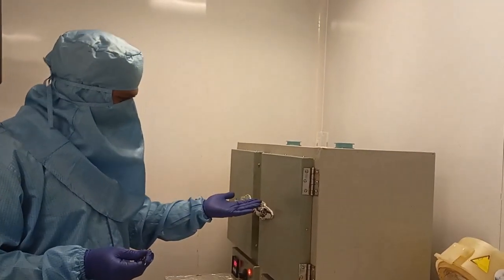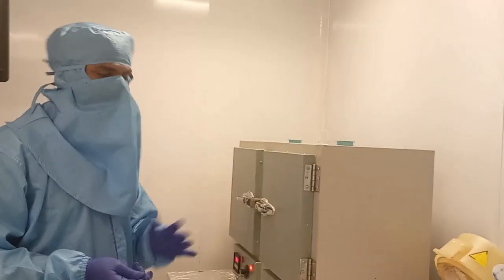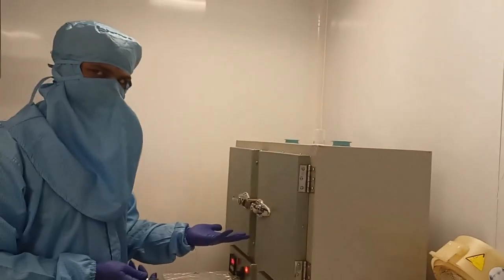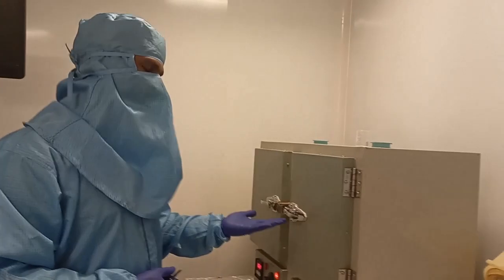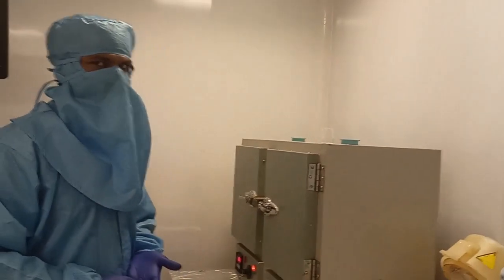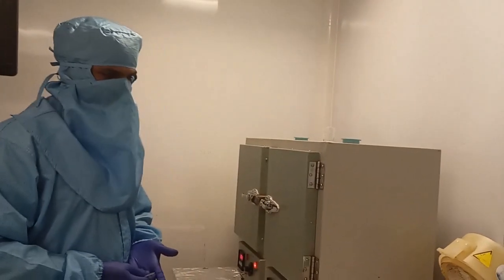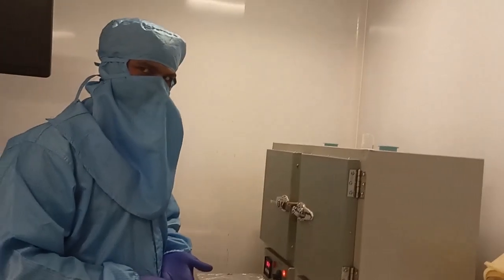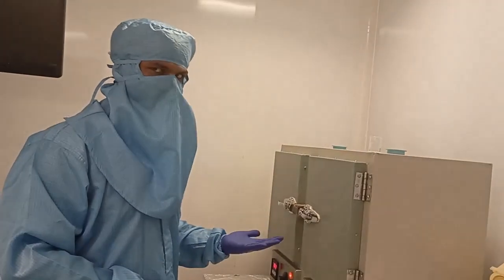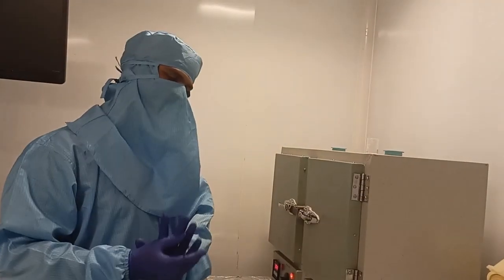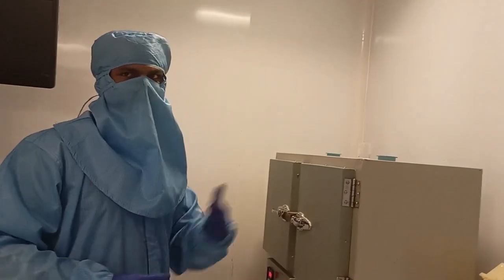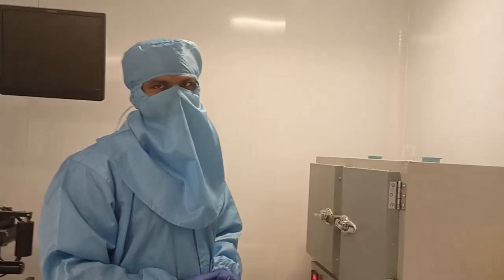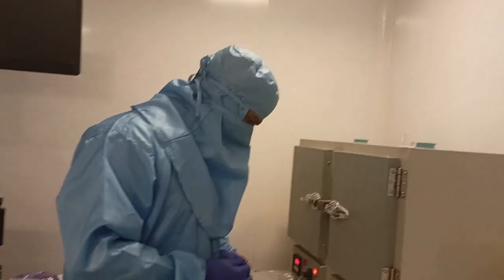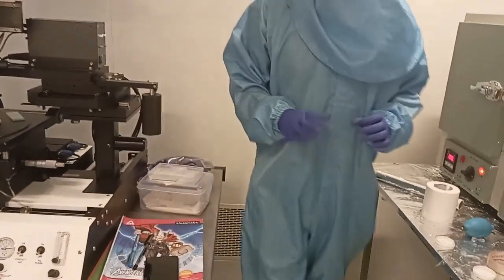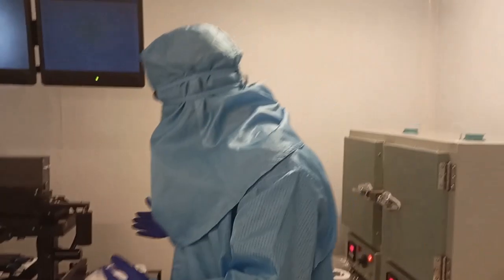If you do it for less than 10 minutes, the solvent may not get evaporated properly. You have to check at what time, because it was previously optimized for 10 minutes. And it was also seen that if it is more than 10 minutes, the photoresist may burn. So I am just shifting the vacuum to this chuck.